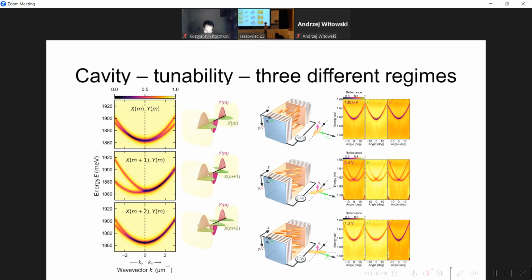This regime was schematically depicted on the left figure. Here we have coupling between modes with the same parity, the same mode number and dispersion relation - here in the kx-y direction, here at the kx direction - and here we have coupling between modes with opposite parity, and finally coupling between modes with the same parity, with the respective dispersion relation for each regime.